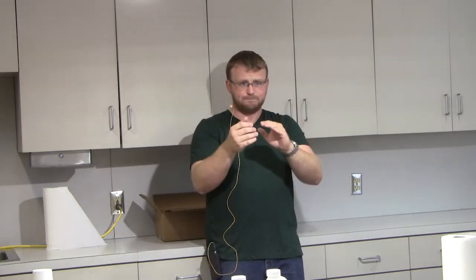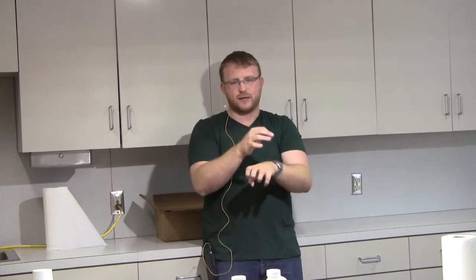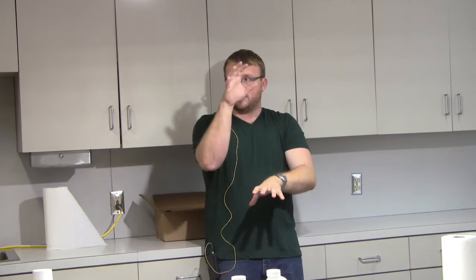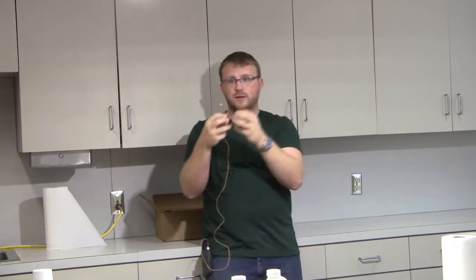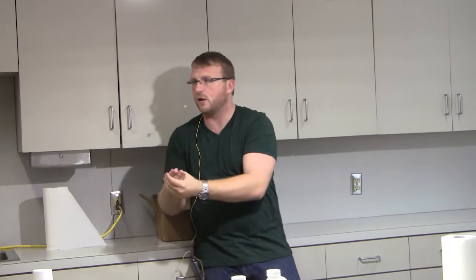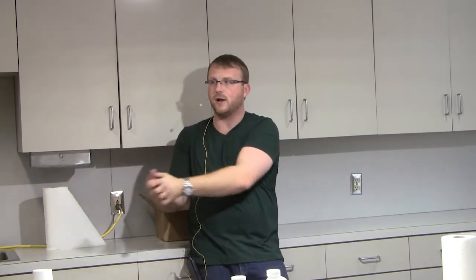But stabilizing is when you take a vacuum chamber, you fill it full of resin or Cactus Juice, and then you drop your piece of wood in with a weight, and it's fully submerged. You then hook up a vacuum to it. What you're going to notice is the wood's going to bubble because you're actually removing the oxygen from the wood. Once it stops bubbling, you equalize the pressure, and all the open membranes of that wood that were oxygen that were sucked out are going to suck in the resin. You then remove it, bake it at 220 degrees for however long, and then you've injected that piece of wood with resin, which has made it solid. So it's really great to do with punky woods or soft woods. So, just to clarify, when it comes out of the vacuum pot, it's still liquid? Correct. That's when you have to take it, wrap it in foil, and put it in an oven to cure it.